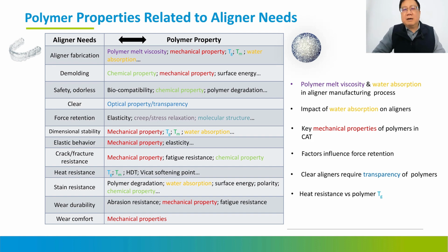And then let's come to dimension stability, because a lot of materials, there are two kinds of materials that are very important. When you do the 3D printing model, a lot of materials have a lower molecular weight. Then dimension stability will be an issue, because when you do pressure forming on the 3D printing dental model, it will change with shrinkage. So you need a good calculation of how to compensate for the shrinkage. Also when you do the retainer, you hope the retainer can be pressed 3 or 4 times to make 3 or 4 pairs of retainers. Then you need more heat resistance and pressure resistance, to avoid dimension stability problems.